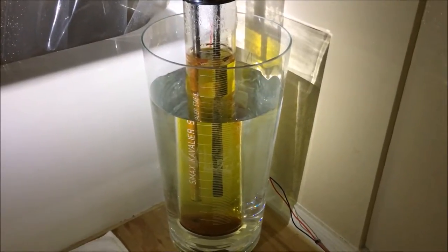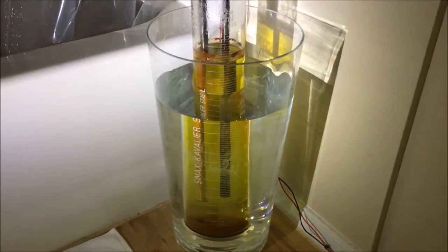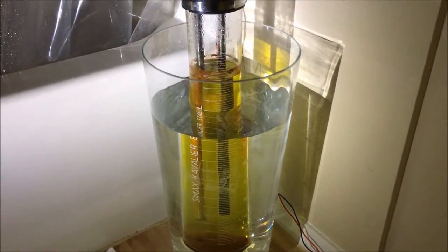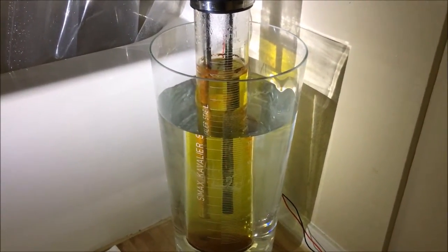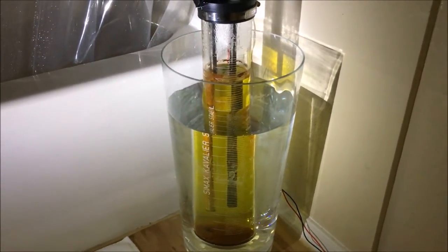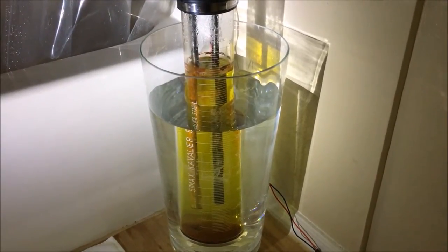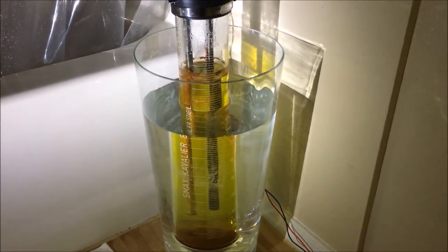Now what I suspect has happened is pitting corrosion has struck on the stainless steel and after doing some research I've determined that to make a viable stainless steel electrode electrolysis system in sodium hydroxide you have to actually keep the over potential extremely low.